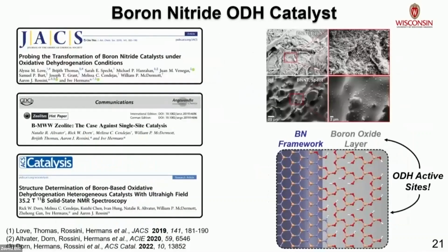Now, we have collaborated with Eve's group over the years, and in particular for boron nitride, what we have been able to show is that under reaction conditions, there's this amorphous boron oxide phase that forms, and it actually directly grows off of the edges of the boron nitride framework. And it is this boron oxide hydroxide phase that are the catalytically active sites for this reaction.